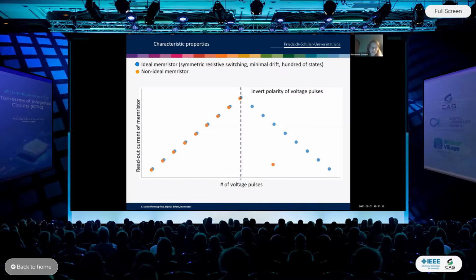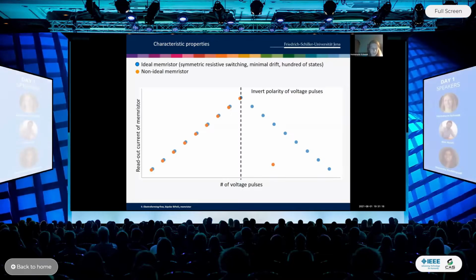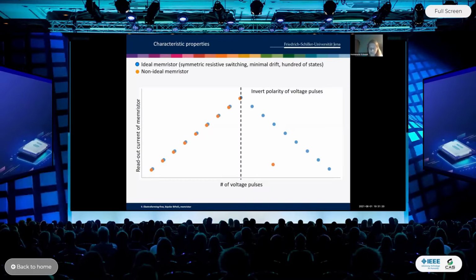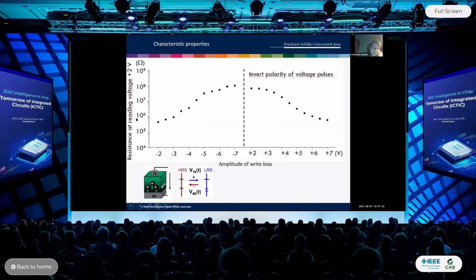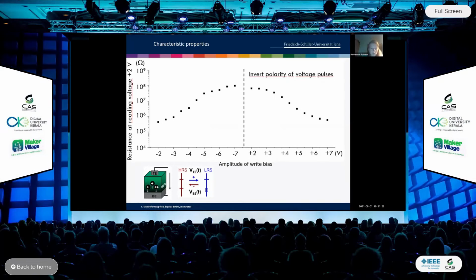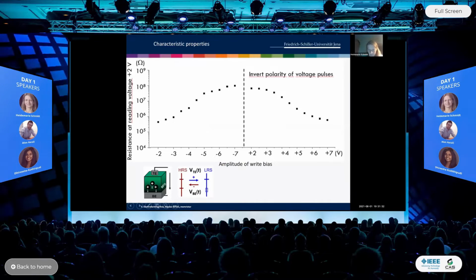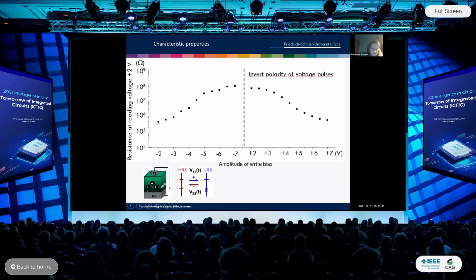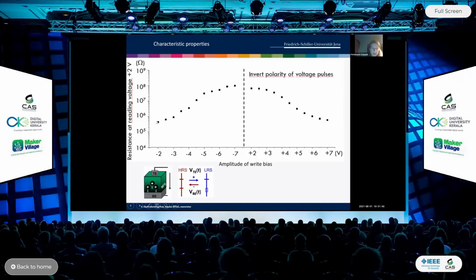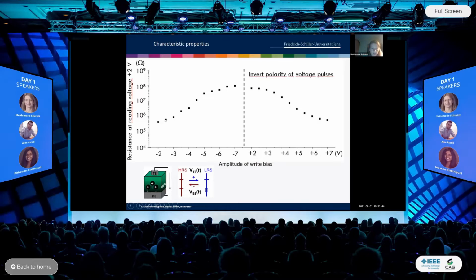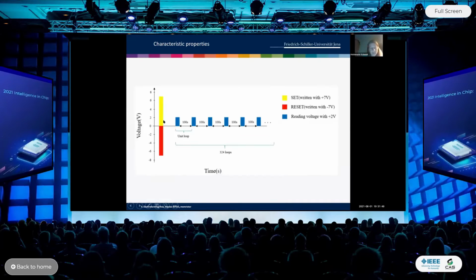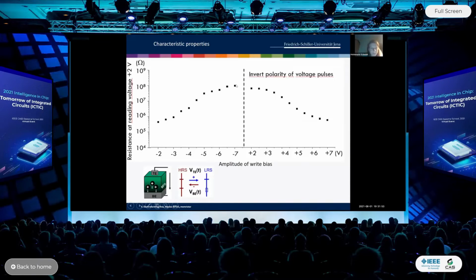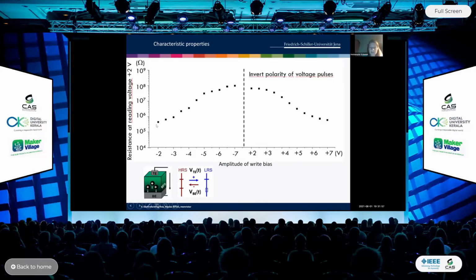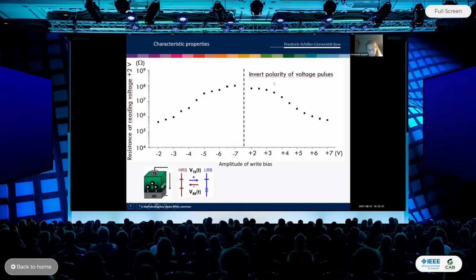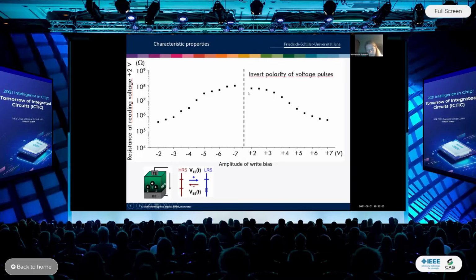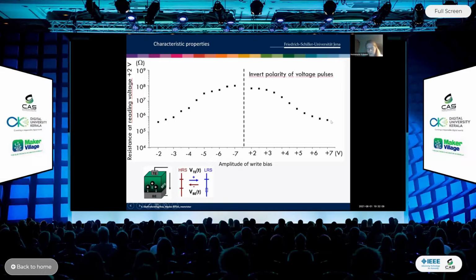I will prove this in the following because we made now for this tutorial a plot which reminds you of the plot I've shown here. Let's call it the definition plot of an ideal analog memristor. What you see here is the resistance at the reading voltage of +2 volt of the bismuth iron oxide memristor, and this is the amplitude of the write bias in units of volt. If we just use a small bias of -2, then nearly nothing is changed. If we then have a larger bias applied, we can increasingly change the resistance state of this memristor. You see here it's up to 2 orders of magnitude change in resistance, that's fine. And then we can invert the polarity of the voltage pulse and again start with a very small amplitude of the write bias, and then we can bring the system successively back to the initial state.